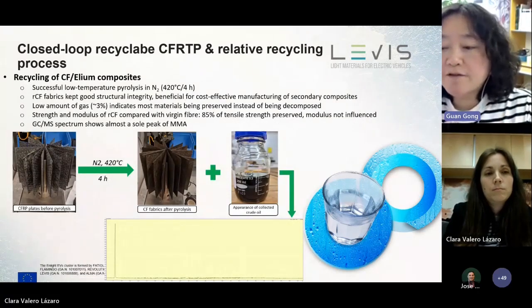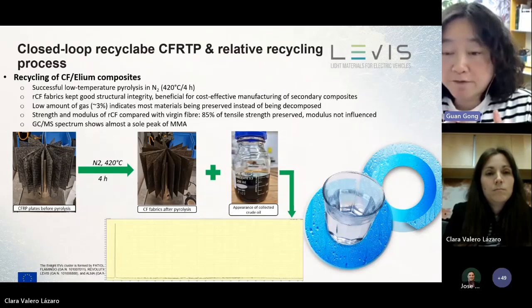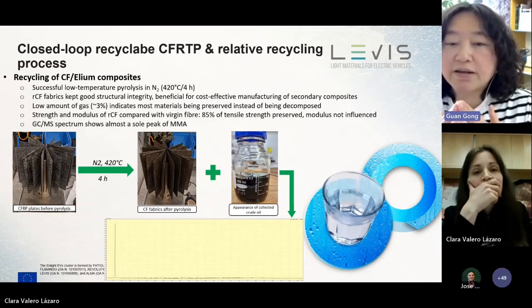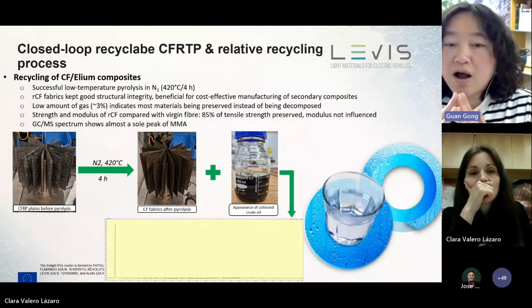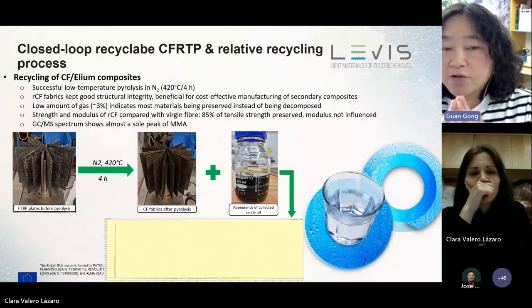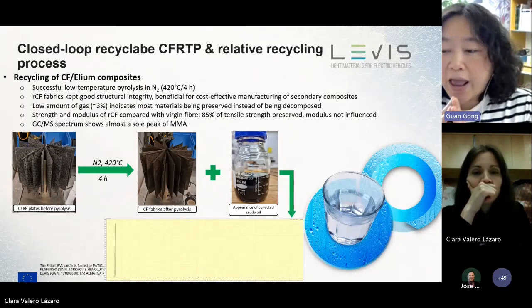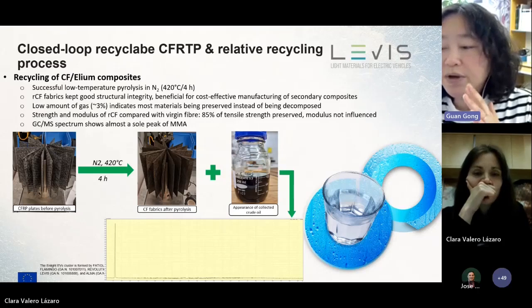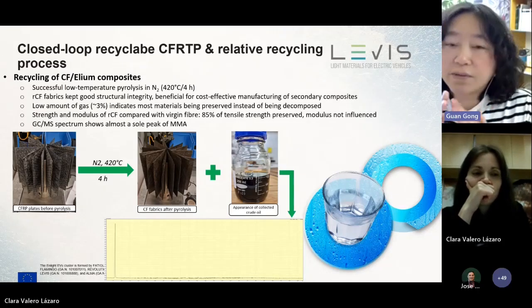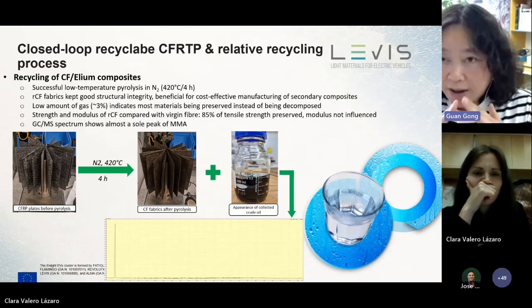So we can also briefly introduce the progress of the recycling of Elium resin based carbon fiber reinforced composite. Here we use a low temperature pyrolysis process in nitrogen atmosphere at 420 degrees for 4 hours. As you can see here, the carbon fiber fabric keeps a good structural integrity after the pyrolysis, which is beneficial for the cost of manufacturing of the secondary composite. And the products out of the pyrolysis process are mainly recycled carbon fiber fabrics and crude oil. And the gas amount is only around 3% of the whole.